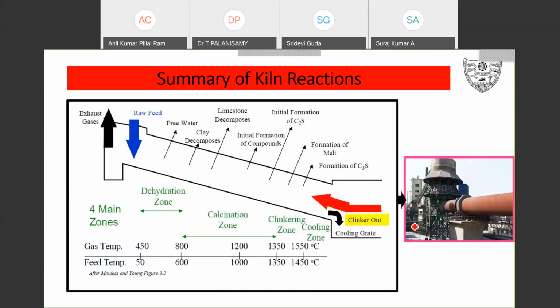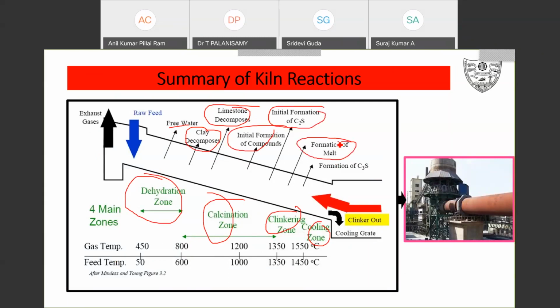Now, this is the summary of kiln reactions. This is the temperature with respect to the product. This is the dehydration zone. You have the calcination zone, the clinkering zone and the cooling zone. What are the processes we have seen? Free water removal, clay decomposition, limestone decomposition, initial formation of compounds, initial formation of C2S, formation of melt, and formation of C3S. The first compound forming in the kiln is C2S. Tricalcium silicate is seen at around 1450 degrees centigrade.